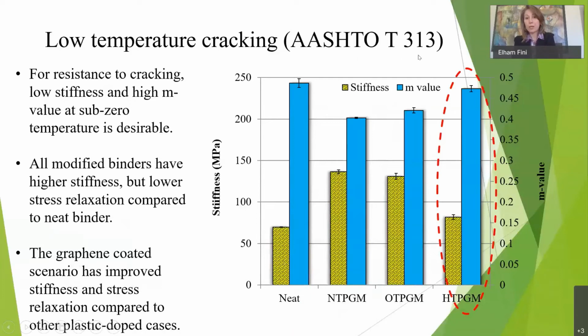That's another AASHTO standard. It's a standard test used by road authorities in all 50 states in America. And we look at two parameters. Here it says for resistance to cracking at sub-zero temperature, we want low stiffness, which is the yellow curve, and we want a high m-value, which is the blue curve. So we want the blue as high as possible and the yellow as low as possible. That helps the road resist the cold winter of Minnesota. So in this case, you actually see that the hybrid performed pretty well.